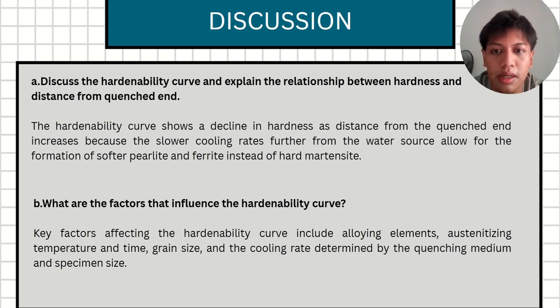from the quenched end. First, the hardenability curve shows a clear decline in hardness as the distance from the quench end increases. This occurs because the cooling rate is slower further away from the water source, and the slower cooling allows for the formation of soft pearlite and ferrite, whereas the fast cooling at the tip creates hard martensite.